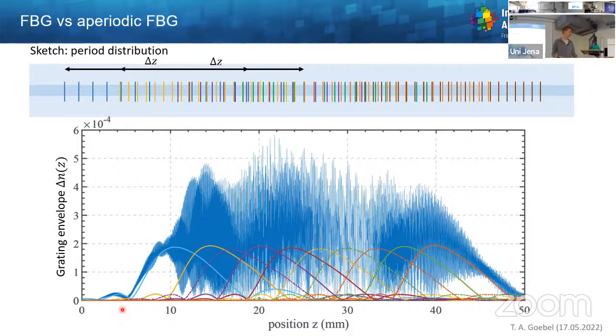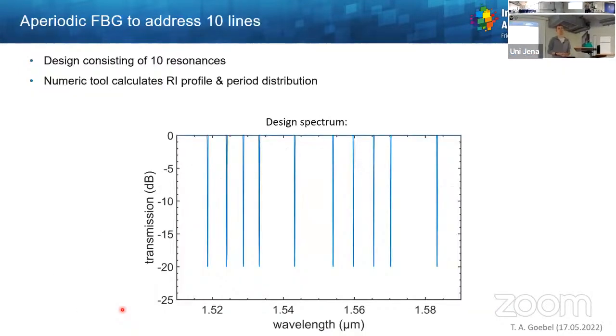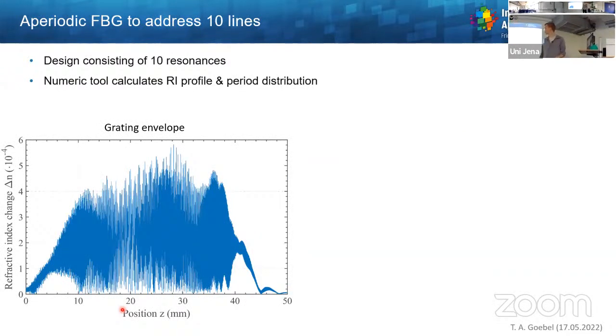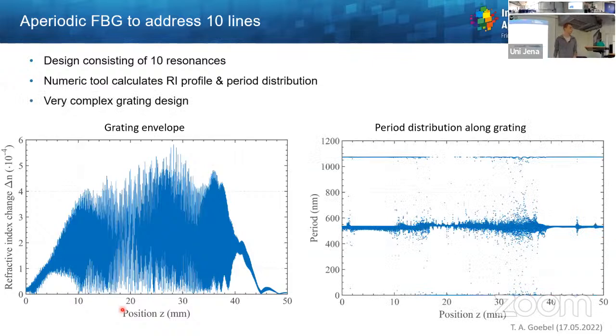The design I've shown here is based on a spectrum consisting of 10 resonances. This is how the initial design spectrum looks. And we do not just purely overlap our gratings, but there is a numerical tool based on the layer peeling algorithm, which calculates our profile and period distribution. So when we take the given spectrum, we get the grating envelope as shown before, and the following period distribution. What you can see here is a basic period of 535 nanometer, and then a large variation around it which does not show any periodicity at all. There are also several phase jumps, which you can see in the top part, or places where periods fall very close to each other.